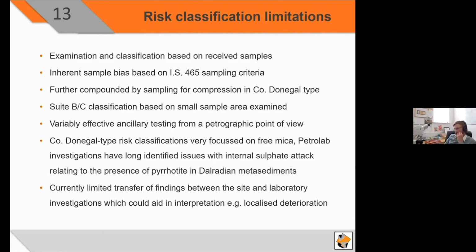There are several limitations that are levied upon us based upon the current standard and our interpretations of the risk classifications. Examination and classification are based upon the received samples. Unfortunately, currently there is an inherent sampling bias, especially noted within Donegal County, where samples must be taken approximately 200 millimeters away from cracks, and with a high sampling bias towards areas which will give good samples for compressive strength. This is effectively masking some kinds of deterioration that we feel like we are not seeing in the samples when related to the structural observations provided by the engineers.